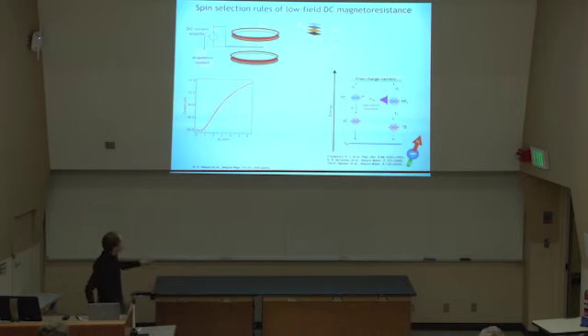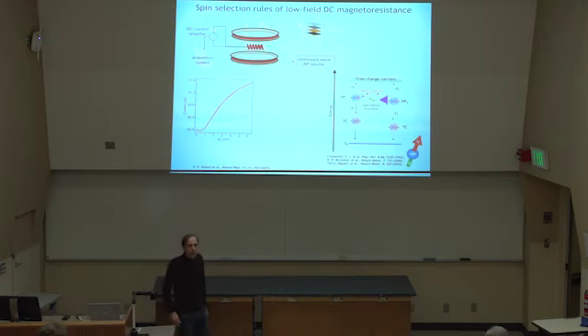How can we test this? That's the interesting data. You repeat this experiment, magnetoresistance measurement, in the same way after essentially introducing a copper coil to your experimental setup, and then you apply an RF radiation. And what this can do is, at the appropriate magnetic field, if you choose the right frequency, introduce magnetic resonance.